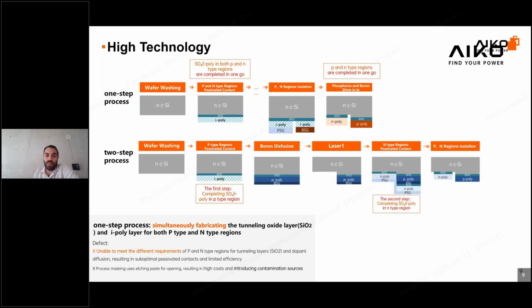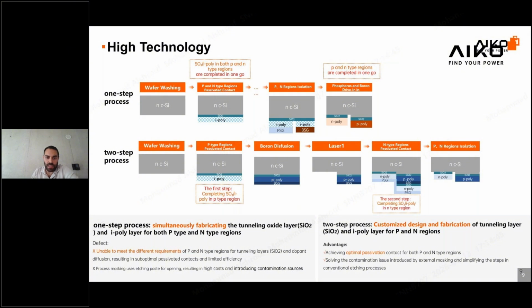And what AIKO has done is separate these two steps of passivation. After washing the wafer, they do the passivation for the wafer, and they form the P junction, normally by doping the boron. Then they do the insulation using the laser, and then, one more time, they do passivation from scratch, and then form the N type, the N region in the cell. So this kind of two steps of passivation gives us improvement in the efficiency and power output of the panel. And this is the main development we have, and it gives us an advantage to make one step further in the back contact technology.